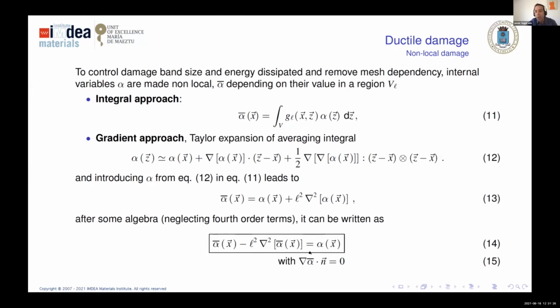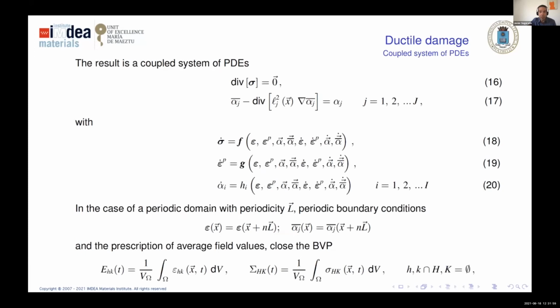What is the difference? The difference is that the source term is the local value of the internal variable. The other difference is that the characteristic length here is a physical parameter, not a numerical parameter. This physical parameter is related to the size of the band in which we localize damage. Unlike in phase field fracture, when we think in linear elastic fracture mechanics, where the correct solution is taking L to 0, in this case L is a parameter we have to consider because it is part of the physics.